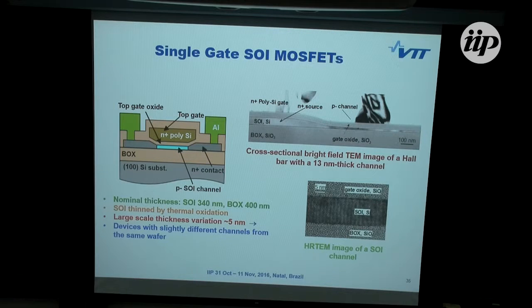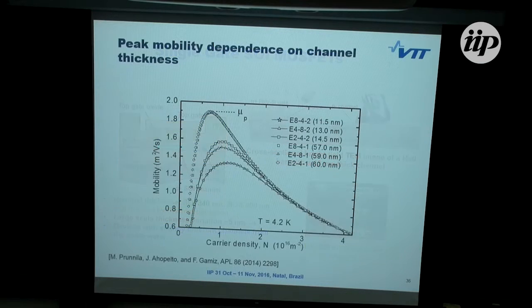And there's a high resolution image also of this channel, and it shows that the interfaces are of very high quality and sharp. To avoid the phonon scattering, because we wanted to see the effect of the channel thickness on propagation or transport properties, we went to 4 Kelvin measurements. And this is now the carrier density and mobility measured from different sets of devices with different channel thickness.